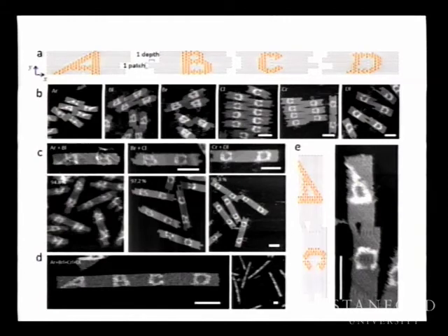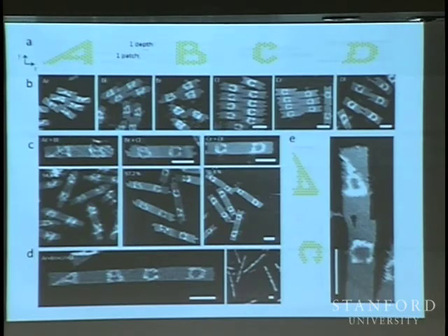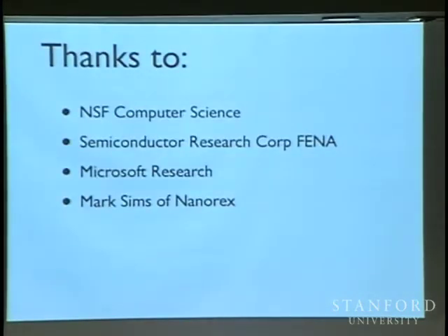And you come up with codes by a similar method, and you can string together 4 different DNA origami that have complementary binding interactions so that you can't even see the suture line between these jigsaw puzzle pieces when they come together. But again, they suffer from bending problems. So these were done so that either they matched at all 4 patches, or they could only match at 2, right? And 2 is too weak and 4 is strong enough. But here they match at 3 because one of the patches is bending. So this is, again, this sort of off-model thing, and the yield of this was, I think, like 45% or something like that. So anyway, that's the end.